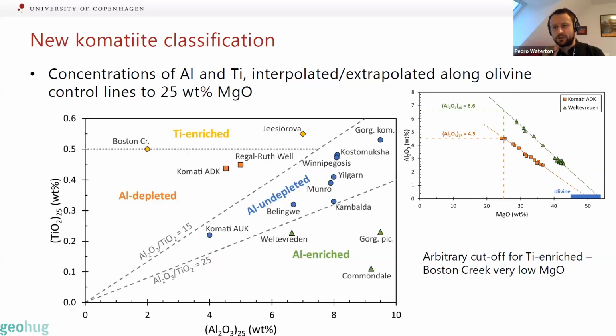And the idea here is just to correct for fractional crystallization effects. We then have aluminium-depleted komatiites being defined by an aluminium over titanium ratio less than 15, aluminium-undepleted between 15 and 25, and aluminium-enriched above 25. The last thing is we have this fourth group, which are titanium-enriched komatiites. And here we just put an arbitrary cutoff of 0.5 weight percent MgO at